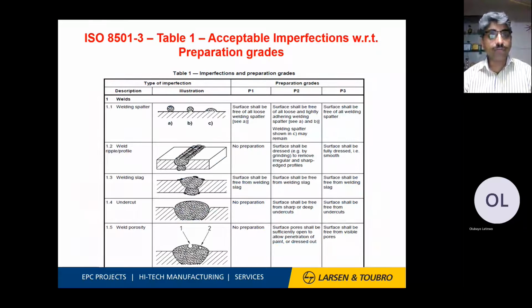Now, this is one slide from ISO 8501-3, which says Table 1, acceptable imperfections with respect to preparation grade. P1, P2, P3 are the preparation grades. P1 is the least surface preparation required, based on the welding parameters. This is one sample. You have more in Table 1. There is a big list of things to be addressed during surface preparation. P3 is the best surface preparation grade.